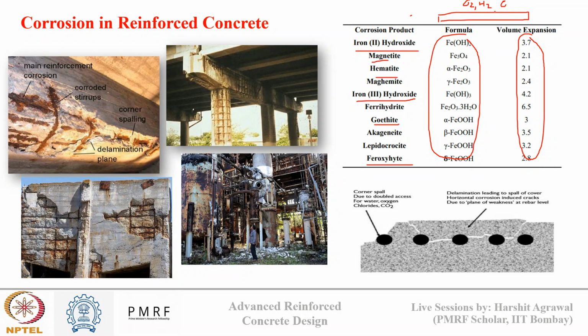Now, inside concrete, as we saw with sulfate attack and other attacks also, if there's high volumetric material present inside a dense concrete, it can lead to tensile stresses in concrete, and if these stresses exceed the strength, they can cause cracking in the concrete. So the same thing is happening here, and you can see this in different images here. You can see main reinforcement corrosion, stirrups corrosion, and due to this, cracking happened, and there's cover spalling and delamination that has happened.